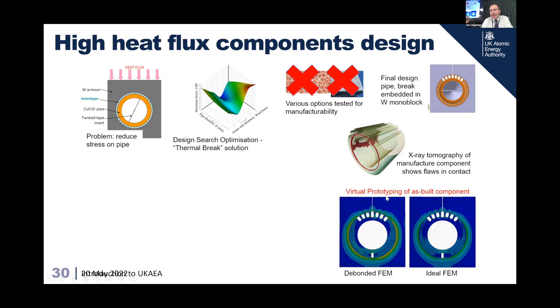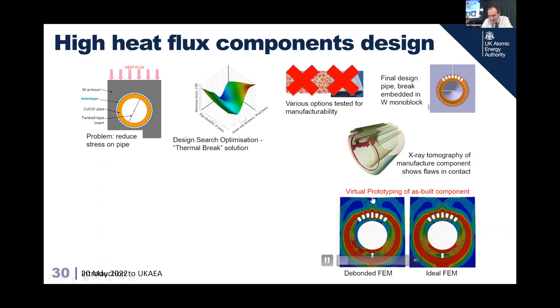So we tested that virtually. The one on the left is the actual, and the one on the right is the design. You can see that whilst the stresses and strains are not actually worse in the actual compared to the design, it's the same sort of color of red. If you look at the top bit of the armor here, it's moving only a millimeter or so, but it is moving at the top because of the difference in thermal expansion.